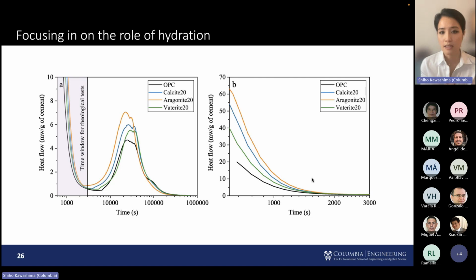And so if you look at that, this is the hydration kinetics, so rate of heat flow. Aragonite has the highest heat flow. And so again, that just indicates that aragonite, likely due to the increased surface area, is having more of a filler effect. Okay, so we kind of already looked at that, but we're just now focusing in on the relevant time window. Okay, seeing the same thing.